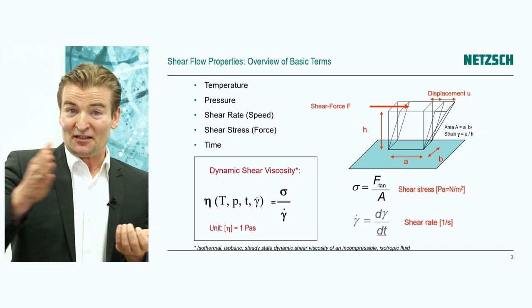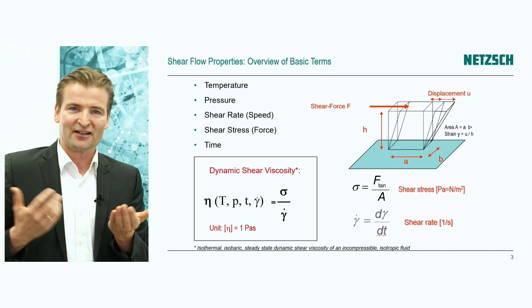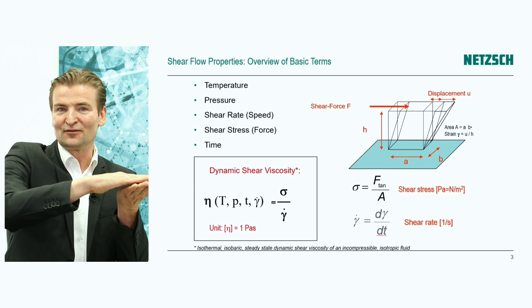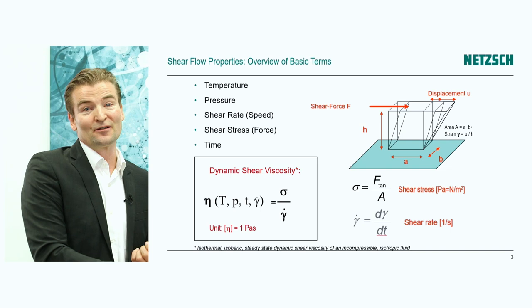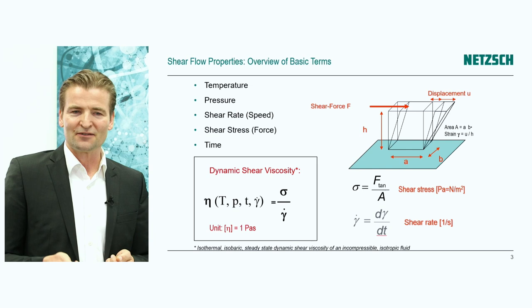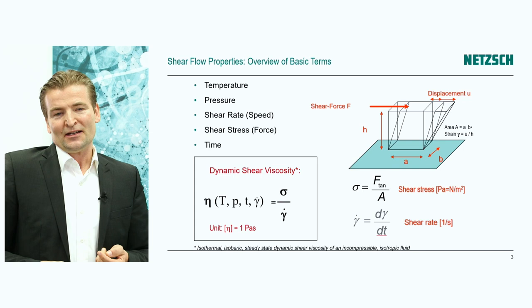If the displacement is time dependent and increasing, the shear strain will also increase. We can then ask: what is the change in shear strain per time? That's called the shear rate. In simple terms, it's the speed of the upper plate in shear flow divided by the layer thickness. Both shear stress and shear rate appear in Newton's law. We measure the inner resistance of the material against an outer force — that's called the dynamic shear viscosity — as the ratio of shear stress to shear rate.